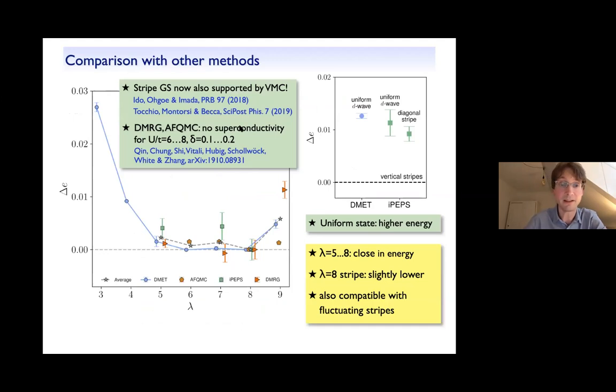Now, let me make some more comments. So a nice thing is that in the meantime, the stripe ground state also got supported from variational Monte Carlo. For many years, there was always this discrepancy between variational Monte Carlo and tensor network calculations, because VMC would usually predict the uniform d-wave state. But then people have improved these calculations by including the stripe order, the spin stripe order, also in the mean field Hamiltonian, to create the projected fermionic wave function, so that in the end, they also found the stripe state as being the true ground state.